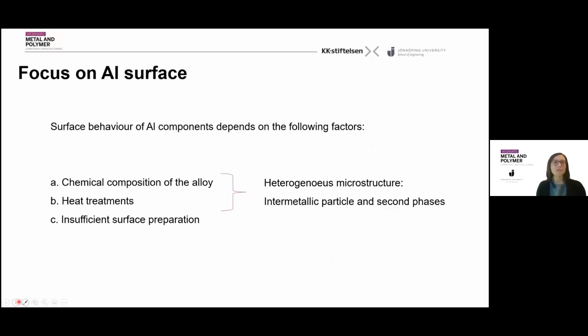The main factors to consider when focusing on aluminum components are mainly three, and they depend on aluminum itself. Aluminum components are very seldom made by pure aluminum; we actually mainly work with aluminum alloys. Therefore, chemical composition of the alloy is really important, but also how those chemical elements are distributed in the material. Presence of heat treatments and microstructural features are really important, because alloys usually show a heterogeneous microstructure. In aluminum specifically, you can have second phases or intermetallic particle precipitation.